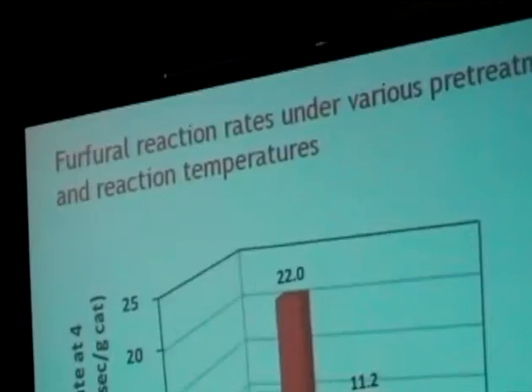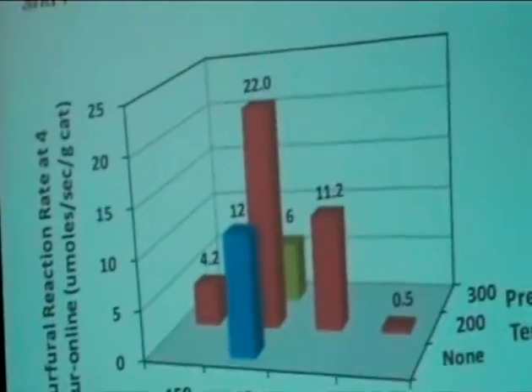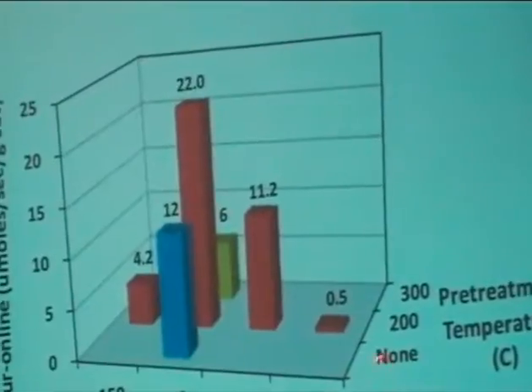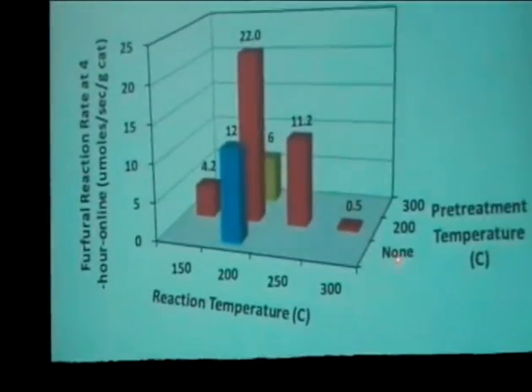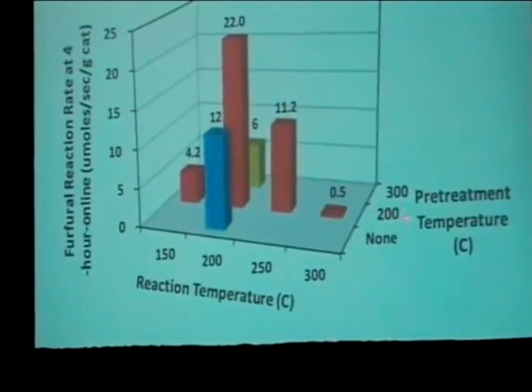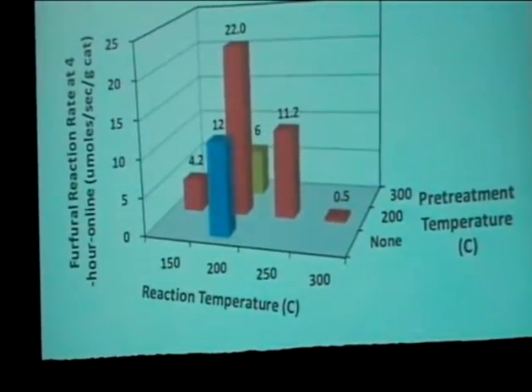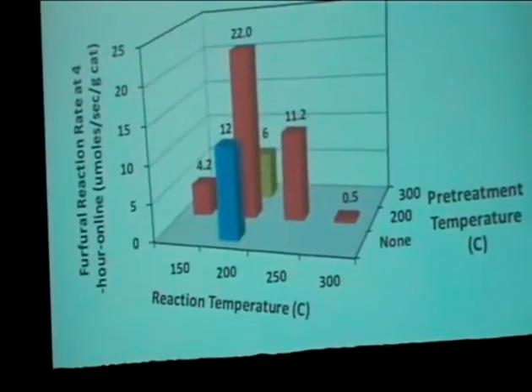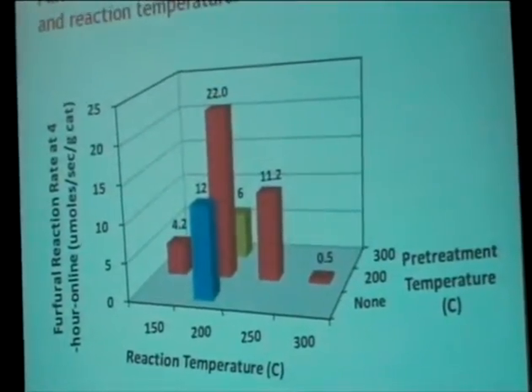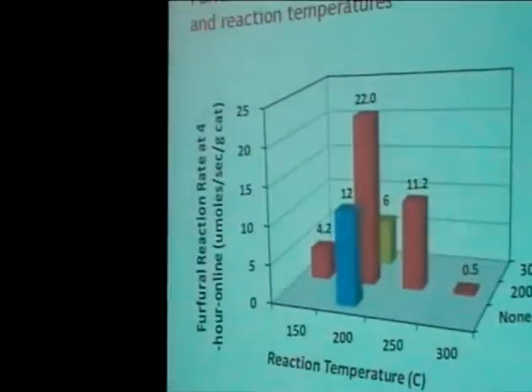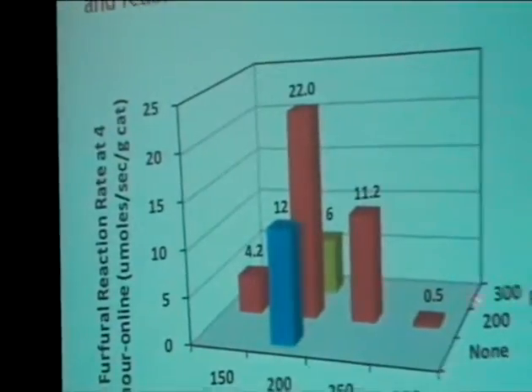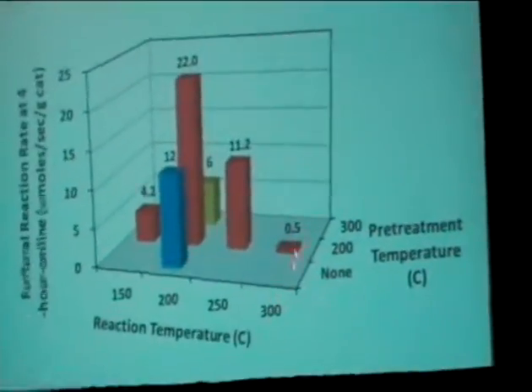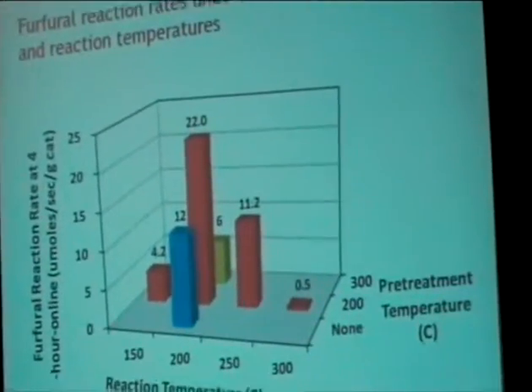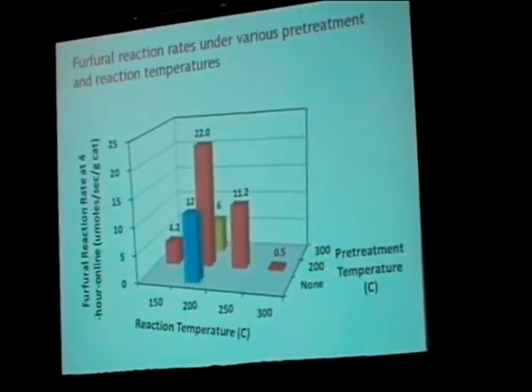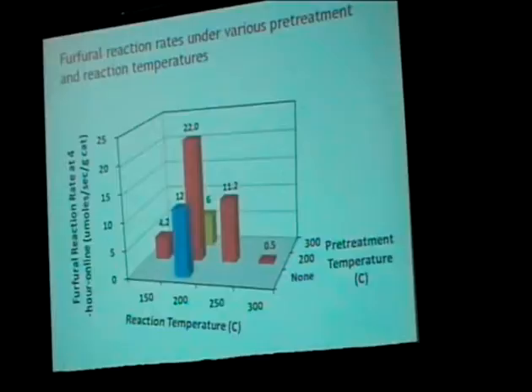Pre-treatment for this catalyst is extremely important. On the x-axis here, we've got the pre-treatment temperature. This is pre-treatment in the presence of hydrogen. You can see that the best pre-treatment temperature is about 200 degrees C, with a reaction temperature of about 200 degrees C. Also, we get the highest furfural reaction rate and the highest yield for this catalyst. If we take it to too high a pre-treatment temperature or too high a reaction temperature, the reaction rate goes down extensively.